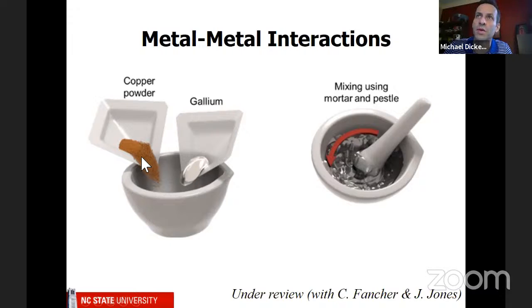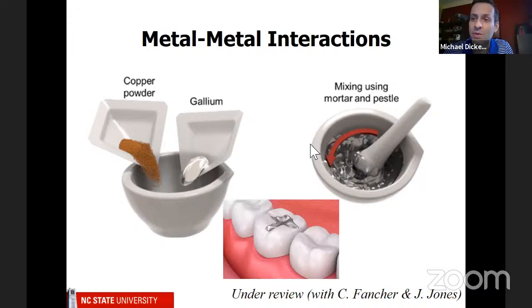So we mixed some gallium with copper powder in a mortar and pestle, just mixed them together. And for a short period of time, they actually have a paste-like quality, but eventually they solidify. Most of you are too young to know this, but when I was a kid and had cavities, they would drill out the decayed part of your tooth and then fill it with what's called a dental amalgam. Instead of gallium and copper, they would use mercury and silver. The dentist would mix them together just like this and stick it in your tooth, and then it would become solid.